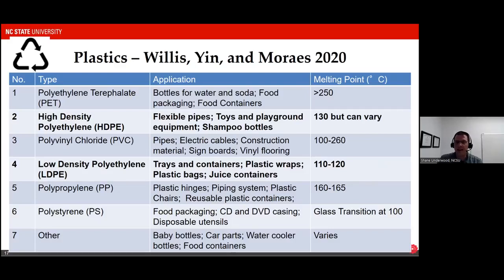The other plastics will tend to melt at much higher temperatures. The ones that are relevant for asphalt concrete tend to melt at higher temperatures. One that's really not very prevalent is polyvinyl chloride, or PVC, largely because of the toxic fumes that come off when you try to heat up PVC at high temperatures, which makes PVC a very non-attractive material for asphalt pavements.